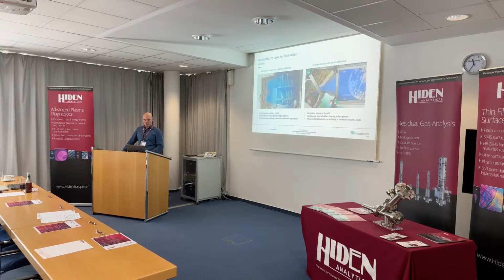We have some droplets or particles, of course, in the films. This is what we expect. And so it's mostly necessary to do some post-treatment of the surfaces. Piston rings, for example, are very easy to process and also easy to grind afterwards, so that is a standard process. And of course, there are applications where you are not able to grind anything or adjust the surface after coating anymore. If you think about gears, then you need initially smooth coatings to make this work.